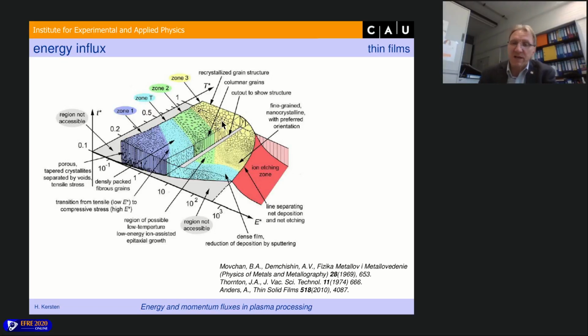That you can do. But sometimes, for instance, for plastic materials or polymer materials, you cannot heat to a very high temperature. But you want to have these crystalline structures also at low temperature, maybe even at room temperature. And you can do another thing. You can introduce or inject energy by ions, for instance, by ion bombardment. If you decrease the pressure or if you increase the ion bombardment, you can change the morphology of the growing film even at low temperatures. So this is interesting. This is just a motivation why the energy influx should be measured or determined for thin film deposition.